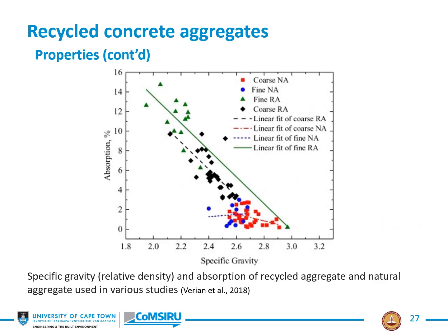This is also well illustrated in this diagram with absorption versus specific gravity or relative density from a whole series of studies. And here you can see, for example, that the natural aggregate, coarse natural aggregate, falls down here in this area. We then have, this is the coarse recycled aggregate, higher absorption, lower relative density. And so we move up to, for example, the fine recycled aggregate up in this region here, which has got high absorption and low relative density.